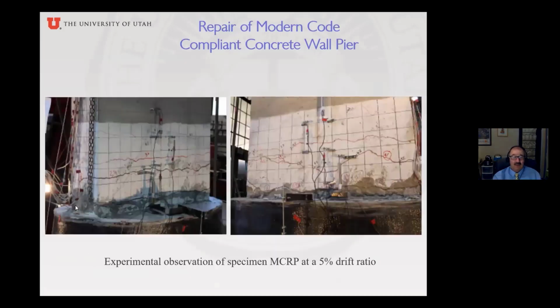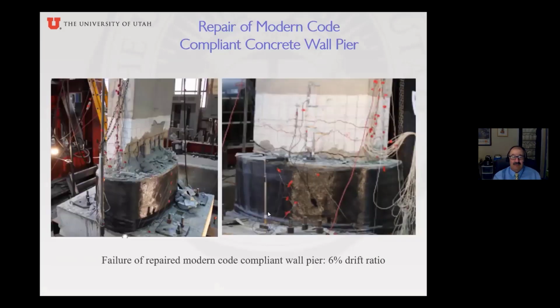And you can see, as we predicted, we failed the wall above the donut. Nothing failed inside the donut. Everything was above the donut. You can see it here at 5%, and you can see it here at 6%. And we could have gone even at higher drifts if we wanted to.